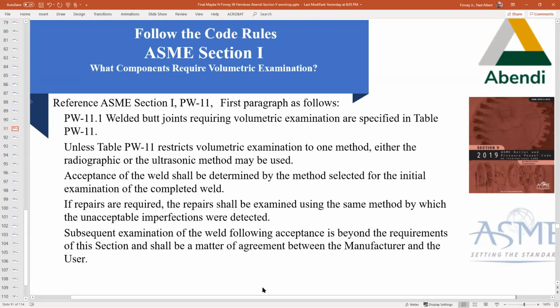Okay, again, we're in Section 1. PW 11 of Section 1, the first paragraph states, welded butt joints requiring volumetric examination are specified in Table PW 11. Now, let me say here, up until about 20 years ago, it used to require radiography, but then they combined it and said volumetric, which means either or. And I'll come back to a little discussion about that and MT and PT as surface exams in a second. Unless PW 11 restricts volumetric examination to one method, either the radiographic or the ultrasonic method may be used. You can do either one of them if it's required a volumetric exam.